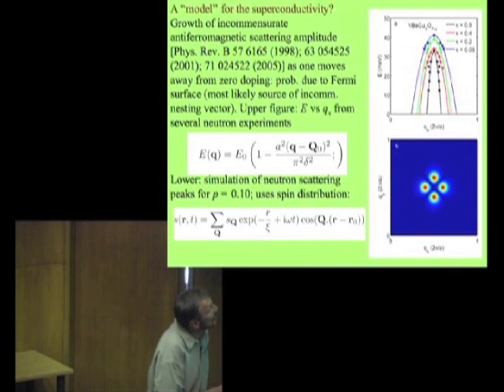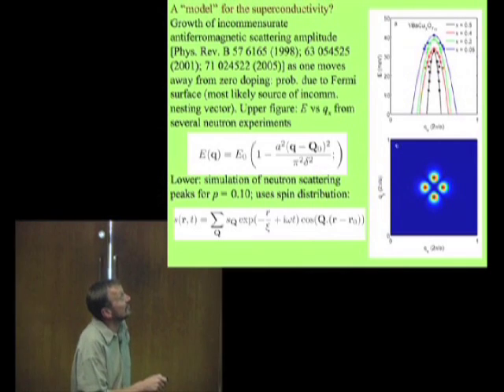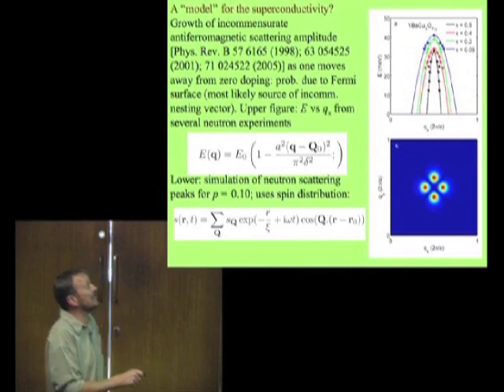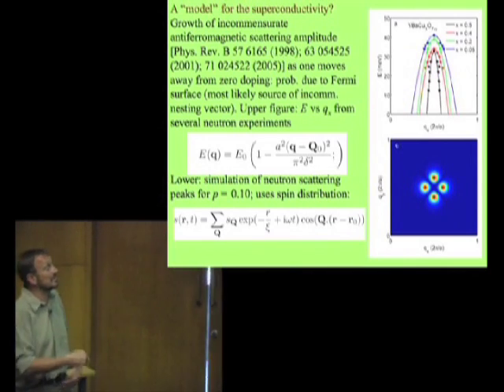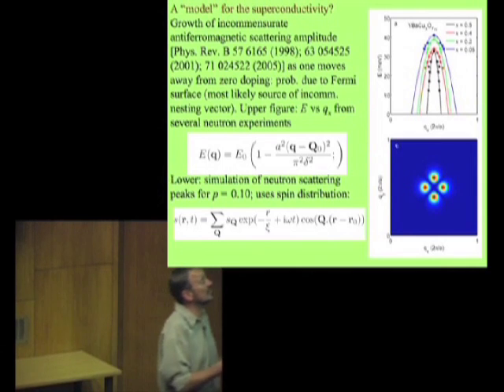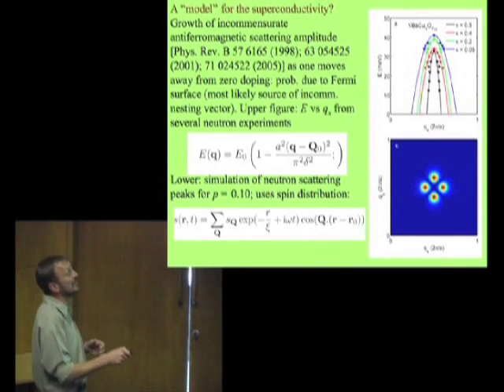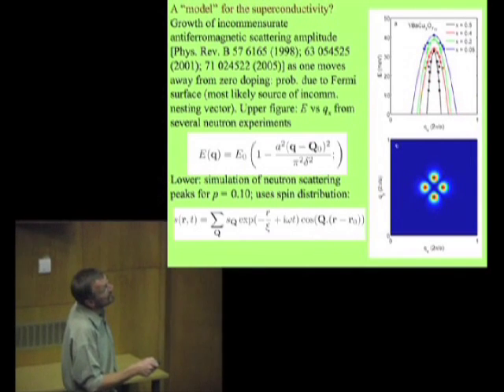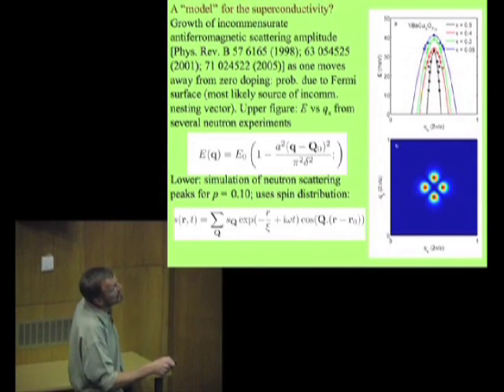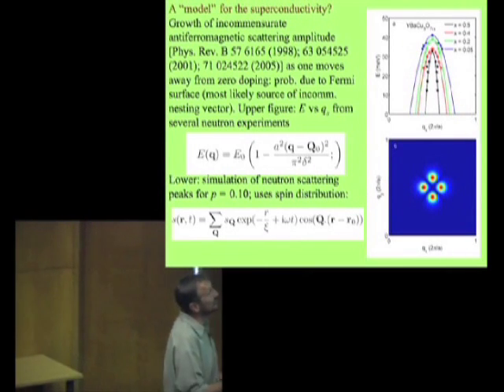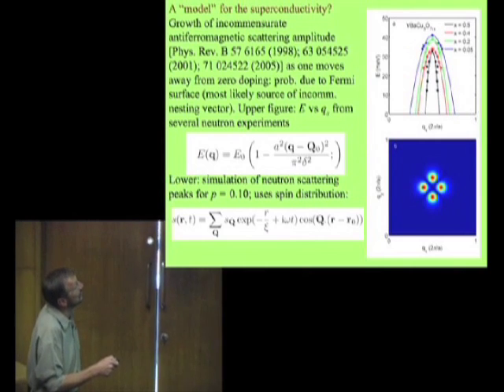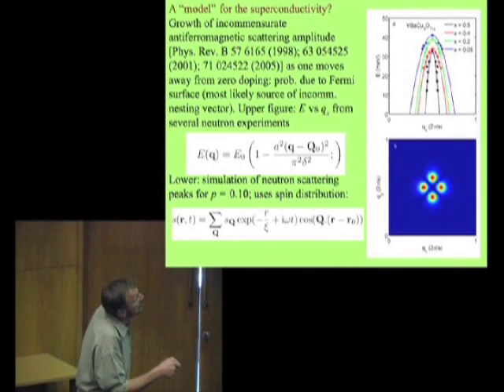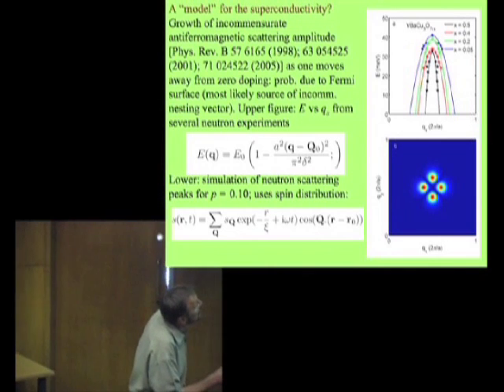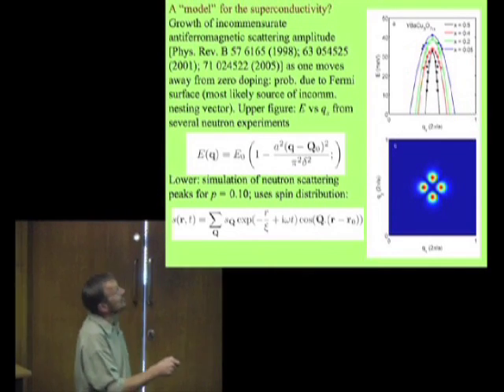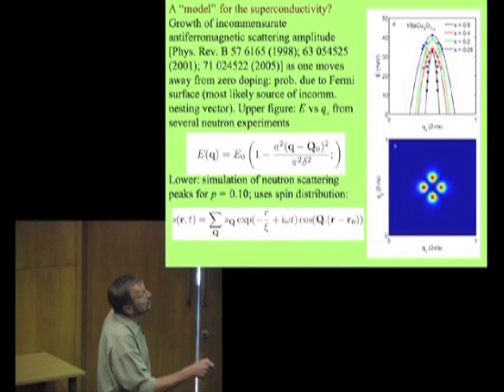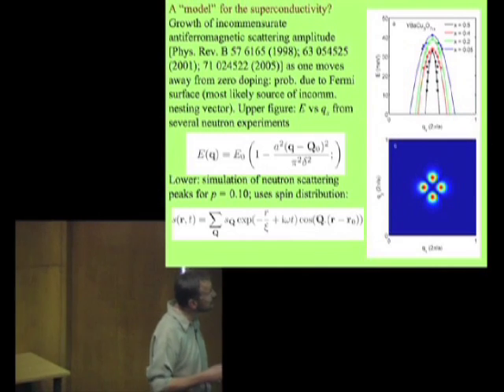Now, where these things touch ground at zero energy is telling you about the new periodicity in the system. This is the periodicity that's giving rise to that Fermi surface reconstruction that I showed you earlier. It's the thing which is involved in breaking the Fermi surface up from its big state into the small pockets. And this periodicity down here, in k space, translates to a real space frequency, which gives you the Fermi surface. So this is the sort of dispersion relationship that the neutron scatterers measure. And it's parameterized by this item delta on the bottom here. And the delta is basically a measure of the spread that these things have when they touch ground.